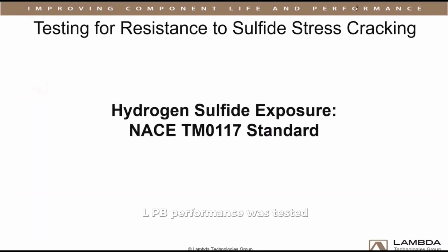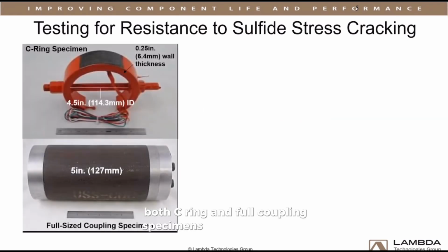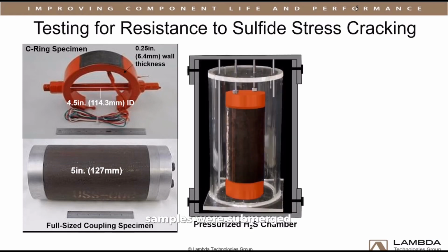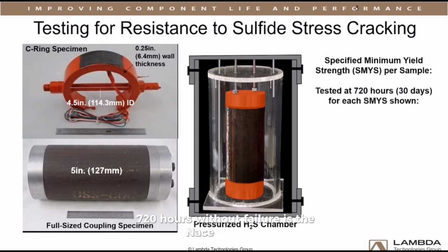LPB performance was tested against hydrogen sulfide exposure per the NACE TM0117 standard. Both C-ring and full coupling specimens were used for this testing, LPB processed and untreated. All samples were composed of API P110 grade quench and tempered steel. Samples were submerged in hydrogen sulfide and pressurized to fractions of the specified minimum yield strength, noted as SMYS in the graphic. 720 hours without failure is the NACE standard to be approved for use in sour service.